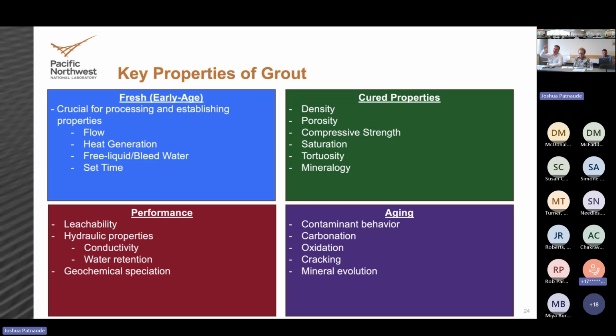If you've got a lot of big pores that are connected, easier pathway, but if you have smaller pores, less likely they're connected, harder pathway for water to move in, and contaminants to move out. And then the overall mineral makeup, because we use that in long-term modeling of how this material will evolve with time, but it also helps us confirm that we made the target product that we were after.